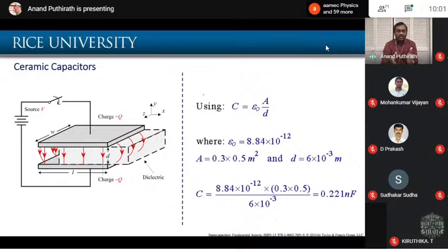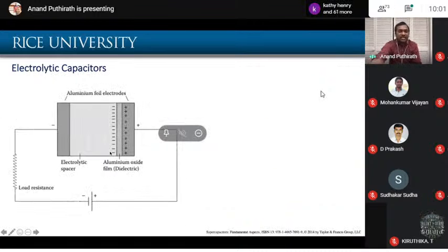And we can see what the limiting factor is here. You have two electrodes and you cannot bring them closer. You cannot reduce D after a limit, right? That is limiting the charge storage capacity here. And you can't increase the area to a large level because you have to incorporate this into small miniature circuits, etc. So these are the limiting factors. The only thing we can probably improve is to decrease the separation so that you can increase the charge storage. And that idea actually brought in the electrolytic capacitors.